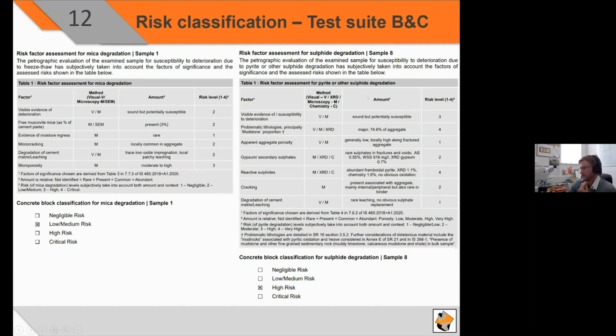If we look at the sulfide deterioration side, some of the main points to consider are the problematic lithologies and mudstone proportion. So this will be the quantitative analysis of the present calcareous mudstones or argillaceous bioclastic limestones. These typically make up a very high percentage of these lithologies, being high-risk classifications. And if we look down at the gypsum, secondary sulfides, and reactive sulfides, this is where the chemical data and XRD analysis of sulfides comes in to influence the classifications.